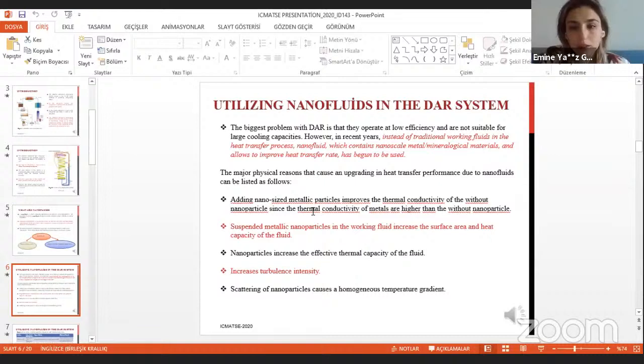In this system, as I mentioned, we have low efficiency and they are not suitable for large cooling capacity. So we use nanofluids for enhancing the efficiency. The major physical reasons that cause heat transfer performance: adding nano-sized metallic particles improves thermal conductivity, which is so important for thermal systems. And suspended metallic nanoparticles increase the surface area. And also, they increase the effective thermal capacity of the fluid and increase turbulence intensity. And also, scattering of nanoparticles causes a homogeneous temperature gradient.